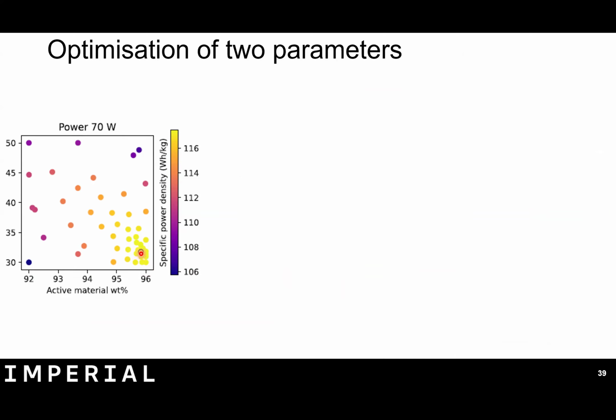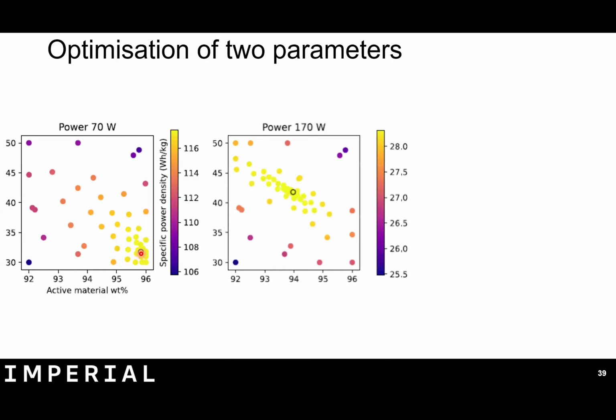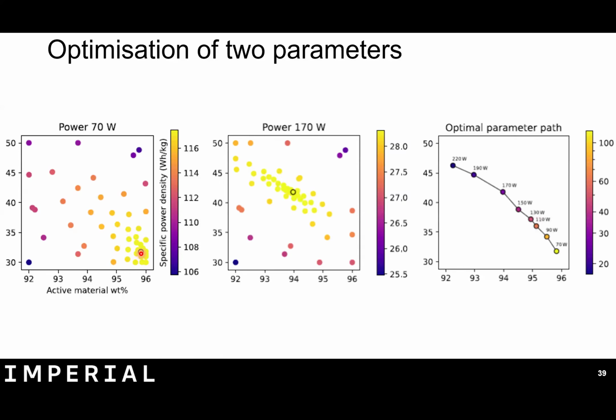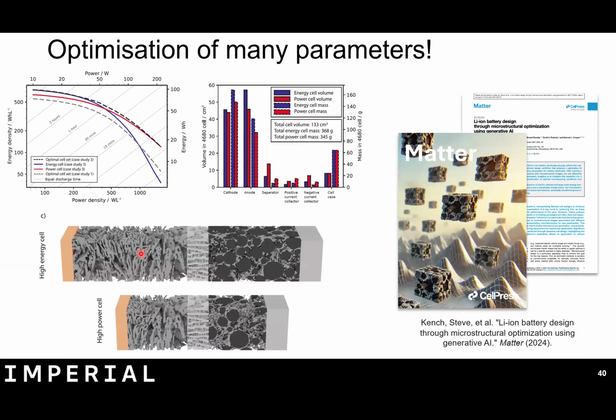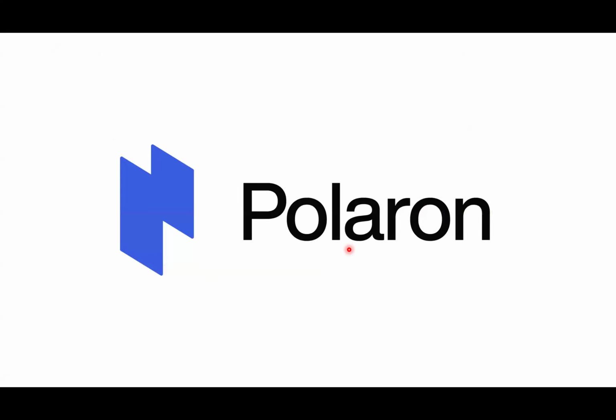Why? Because for both axes, the story is the same. Transport is not very limiting at low rates. So you don't need much help with your electronic or ionic conductivity sensitivity. But as power increases, these things become more important, and you can plot a path through parameter space showing you what your optimal cell design would be for a particular combination of demand. And you can generalize this to many more parameters that you might use to design a cell. And ultimately, you can check out high energy or high power cells based on a range of manufacturing options, including things like the slurry composition and the calendaring metrics and the drying rates.